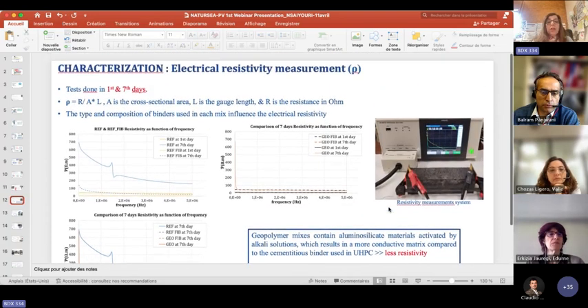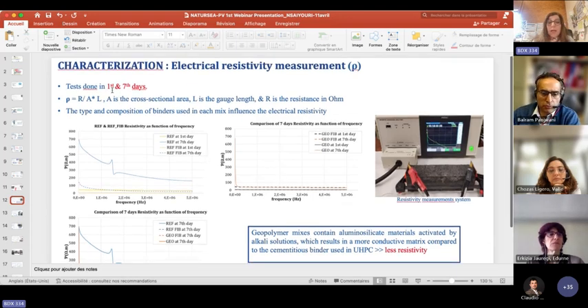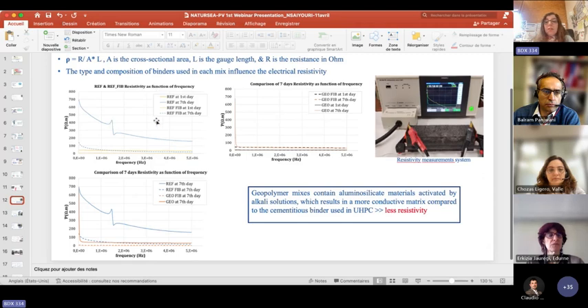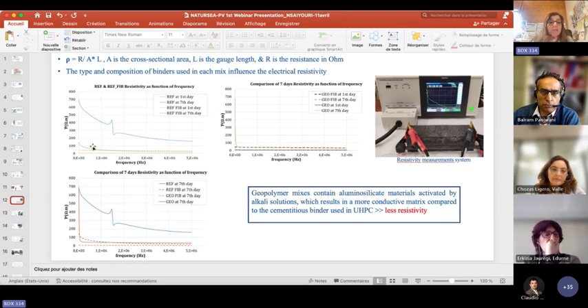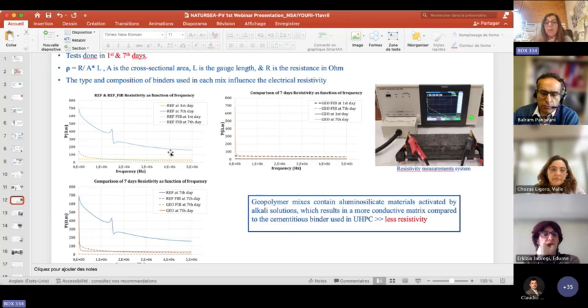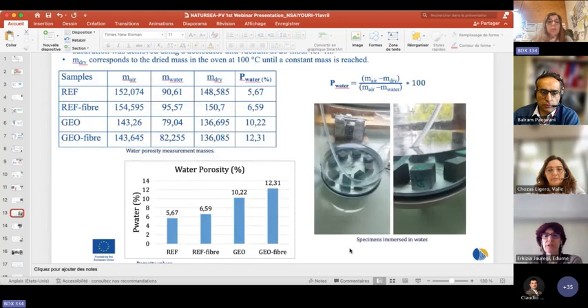We have also tests with electrical resistivity, which were done for the first day and 7 days. That resistivity measurement can show that geopolymer mixes contain aluminosilicate materials, which are activated by alkali solution, that result in a more conductive matrix compared to the cementitious blend, and this is why we see less. All the curves here for geo have less resistivity. This is the measurement of resistivity, which is the opposite of conductivity. So the obtained materials are very conductive, and so resistivity is very, very low in geopolymer mixes.